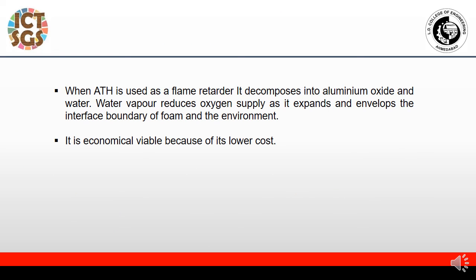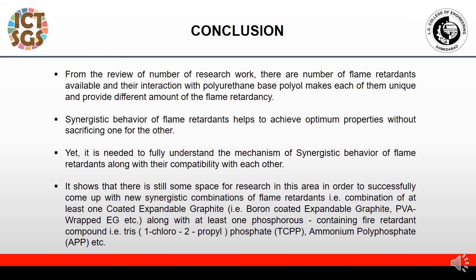When ATH is used as a flame retardant, it decomposes into aluminum oxide and water. Now water vaporizes and it reduces the oxygen supply as it expands and envelops the interface boundary of the foam and the environment. And these are also economically viable because they are lower in cost.